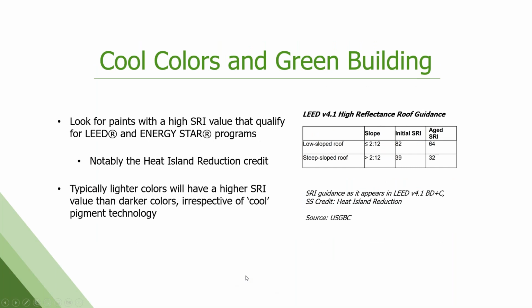Again, I'm sure a lot of you on the phone are more intimately familiar with LEED than I am, but I believe this is the current requirement. It is by low slope and steep slope. Low slope can only get to this 82 value with white. Nothing else really qualifies. Steep slope is 39, which allows you to play in the range of colors and lighter. But the lighter the color, the higher the SRI, even with cool pigmentation. That still holds true.